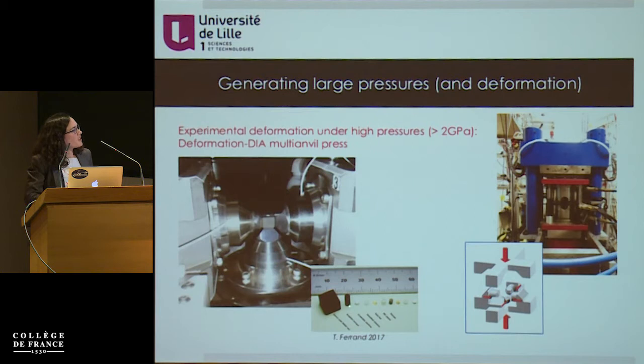And it is within a confining medium that is this cube here, and you have a furnace to heat the sample. And this confining medium with the sample goes in between 6 anvils that are going to press on the sample and impose some pressure. Now you can control also the top and the bottom anvil to shorten the sample, for instance. And this will allow you to do some deformation under the pressures of the Earth's mantle.